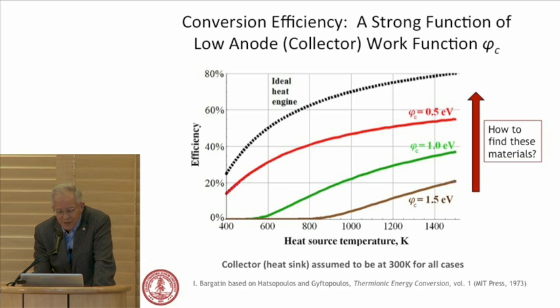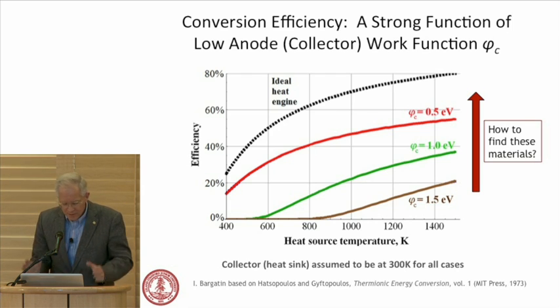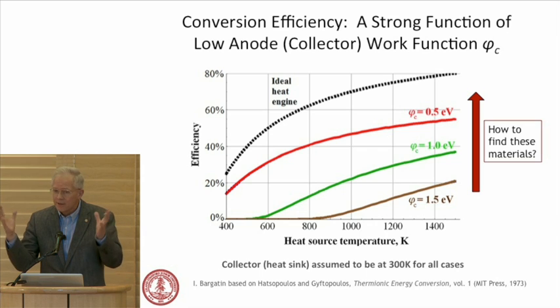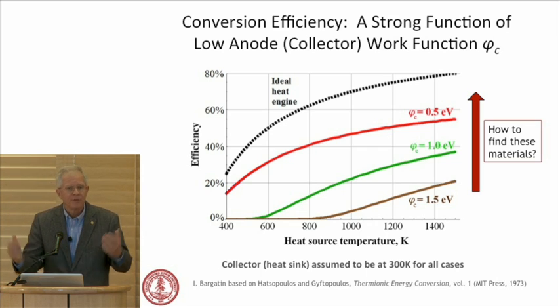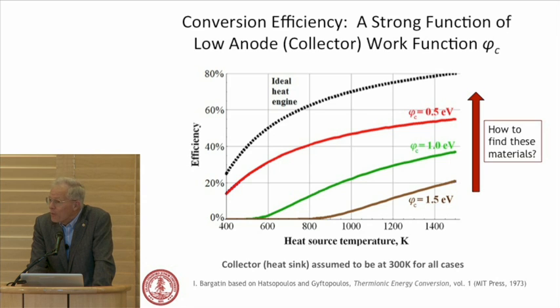If you look at the efficiency of the thermionic converter with the cathode temperature on the x-axis and efficiency, these are ideal efficiencies without losses. This is the collector or anode work function. Going to very low work functions is important. Nanocrystalline diamond has been under 1 electron volt. In fact, we'll report things that are on the order of 1 eV, and these efficiencies are, in context, we may be a topping cycle on that Ivanpah plant. We may not replace the conventional heat engine. Our reject temperature could be quite high.